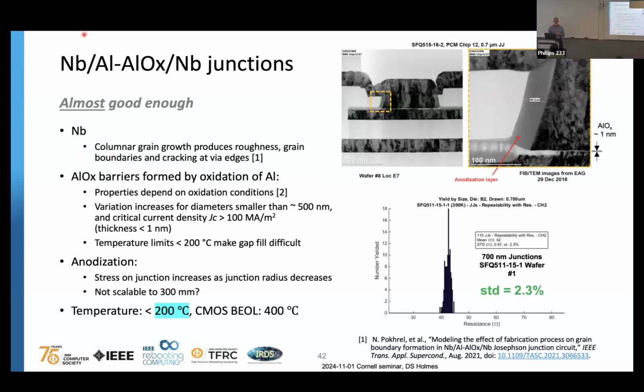What's done now? There's a process, the dominant process for digital superconductor electronics, that uses niobium as the metal. So you've got some niobium here, and then aluminum gets deposited on top. Then the top, say, nanometer of aluminum gets oxidized in a chamber, and then you deposit niobium on top. These have been dominant since maybe the 1980s. They're almost good enough, but they're not going to take us forward. That's my take on it. Part of the problem is you have niobium columnar grain growth and rough surfaces, and I'll show more in the next slide about that. You get cracking at via edges. The aluminum oxide is just a mess.